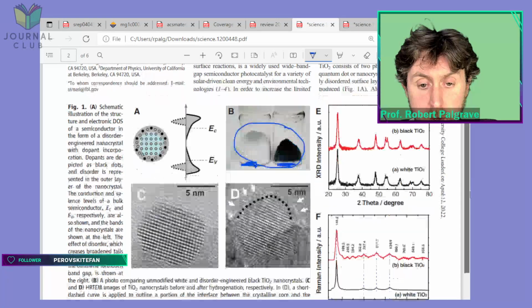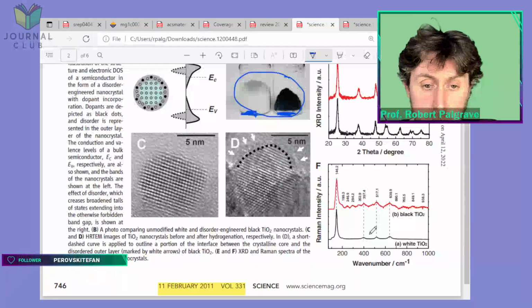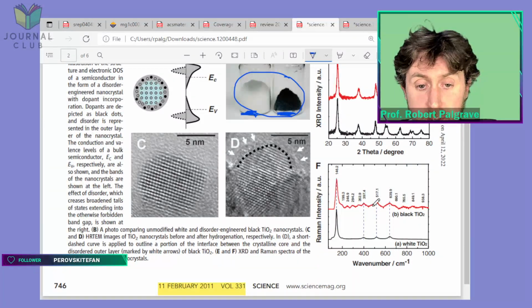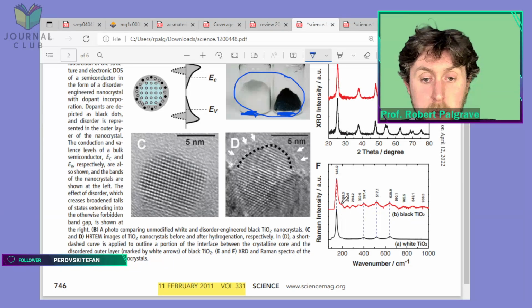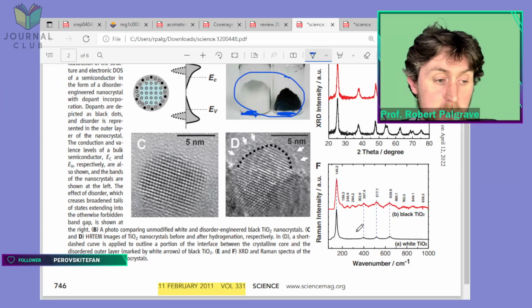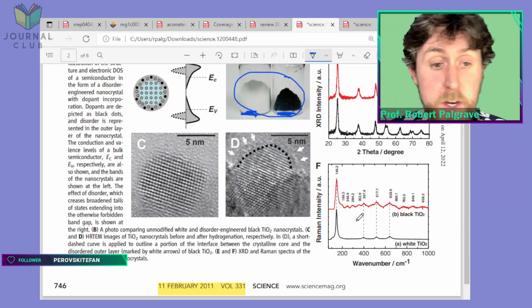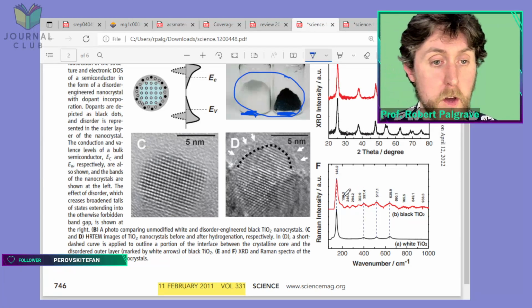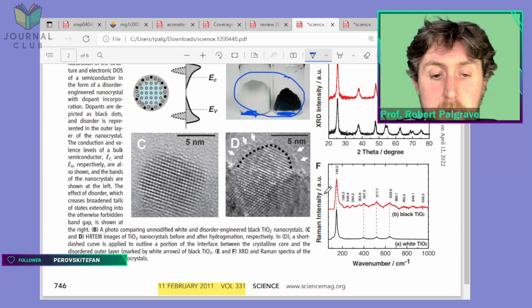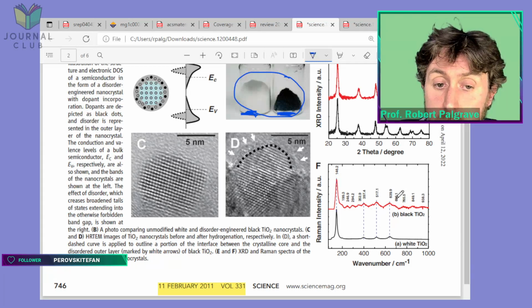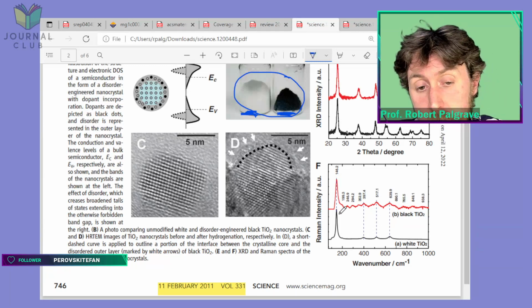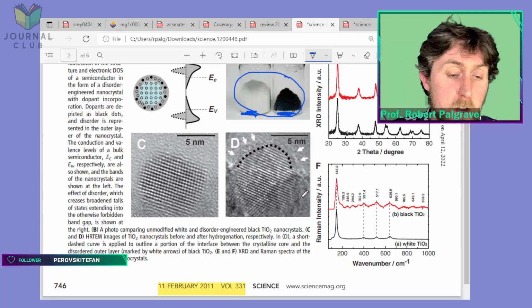If you look at the Raman peaks here, you can see there's a few additional peaks. I think it's difficult to understand what they are, but the main peaks of TiO2 are still present. So Raman tells you about the vibrational properties, and can be used to identify what material you have. And so the vibrational properties, there are some differences, but they're largely unchanged.